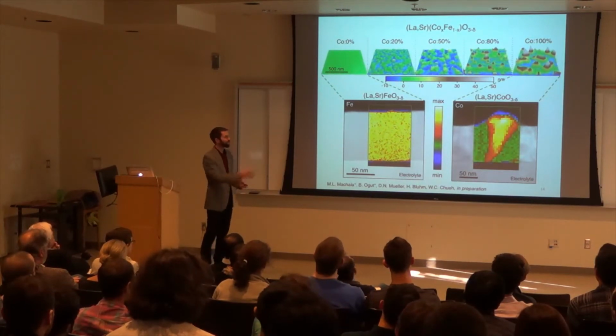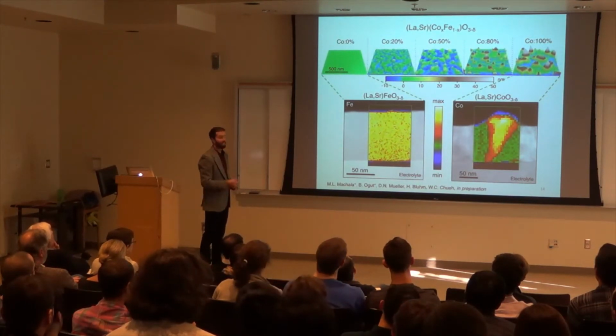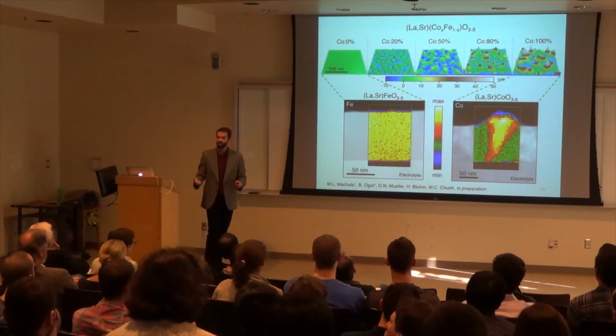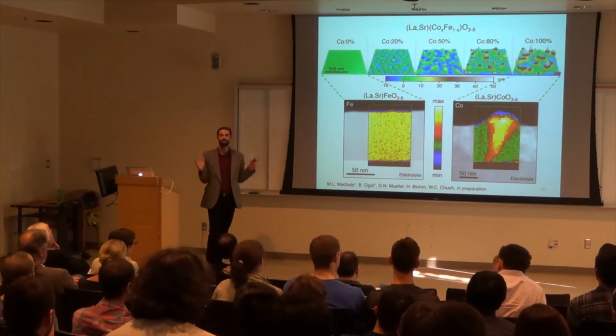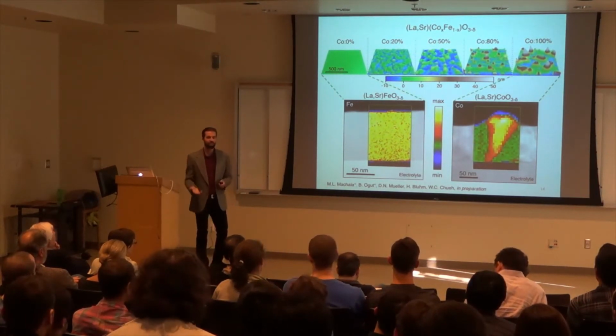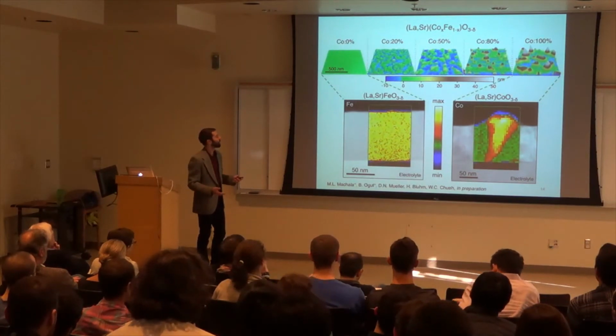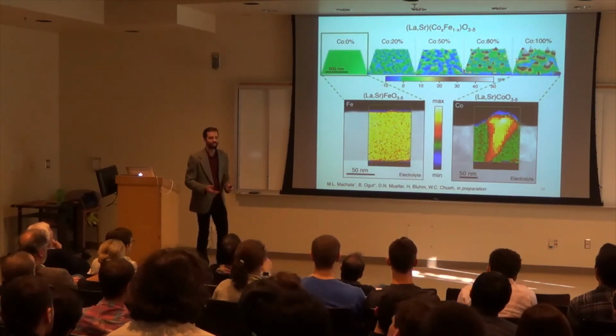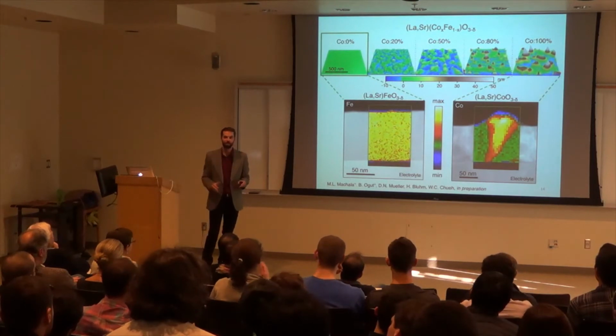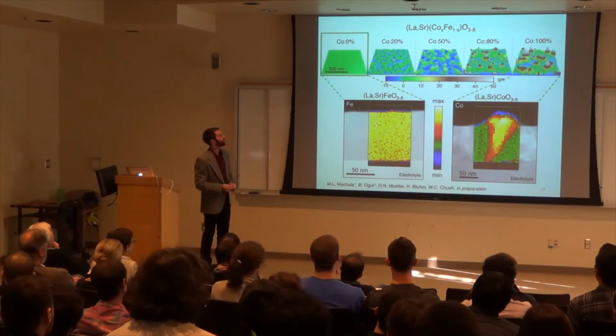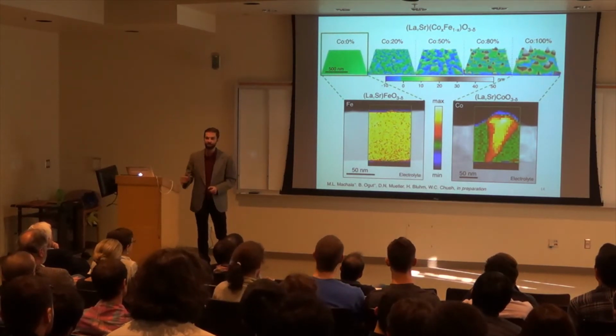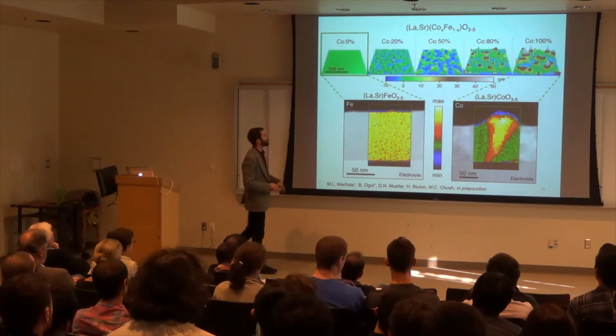So this basically tells us that things that contain a lot of cobalt are inherently unstable, particularly the bulk. So you can imagine the surface being a little bit even more chaotic. So to study the surface, what we want to do is focus in on one specific, very well-defined surface. And so what we do is we study the one without any cobalt in it. So this is going to be really important going forward.